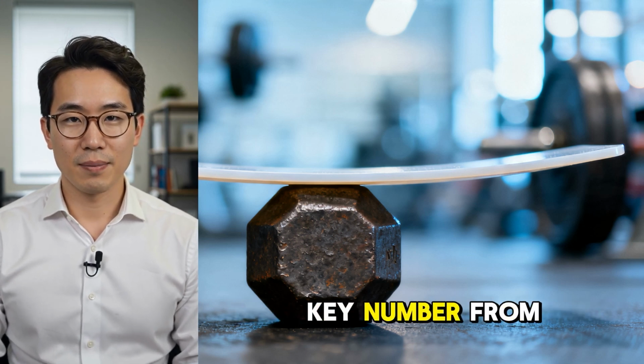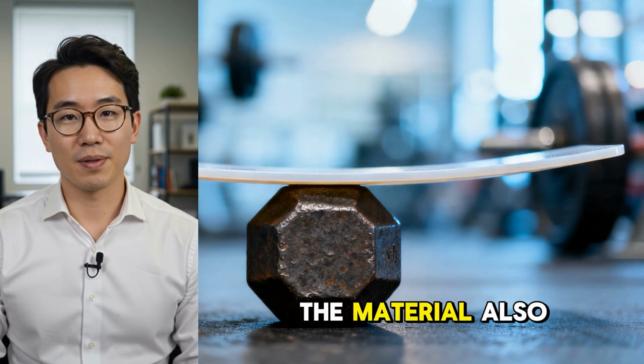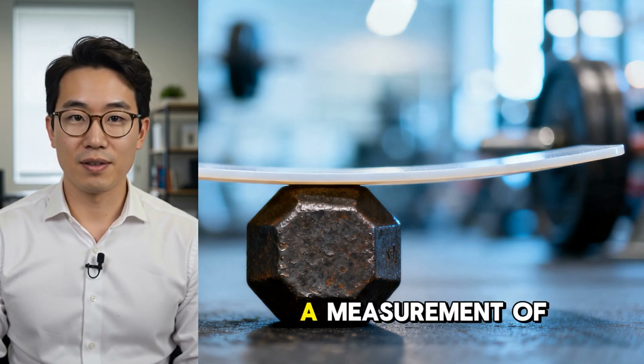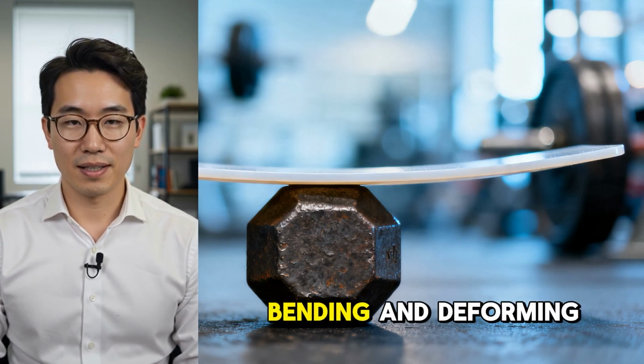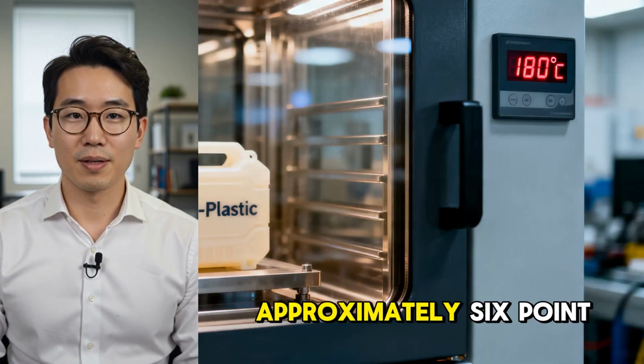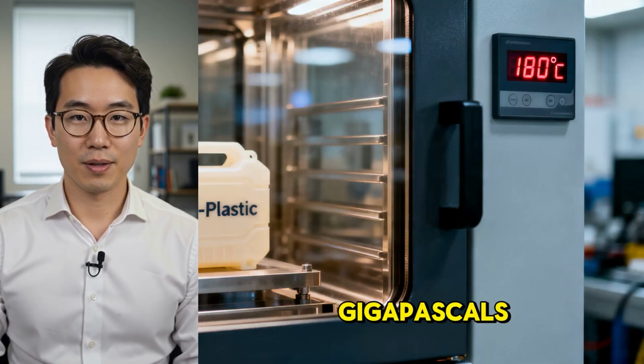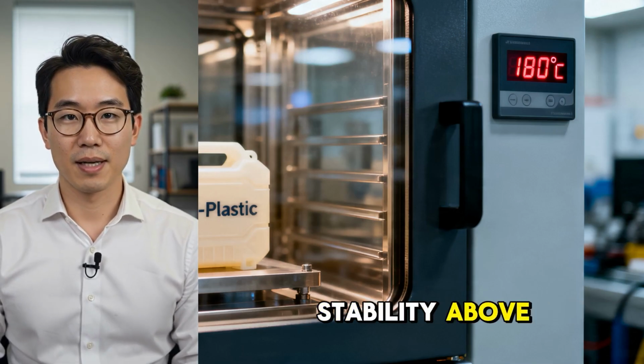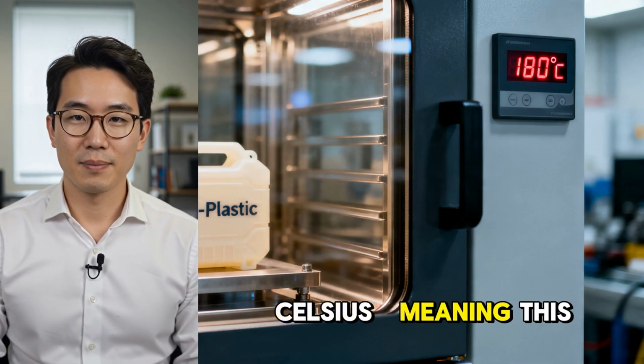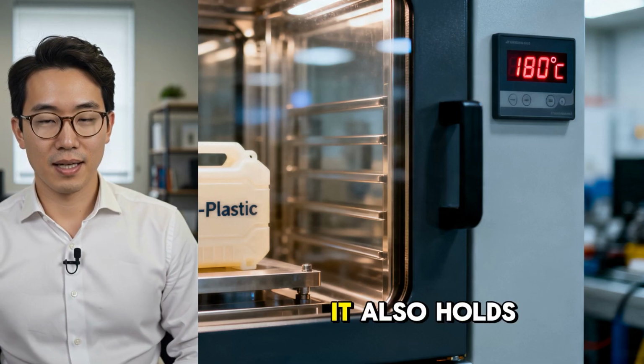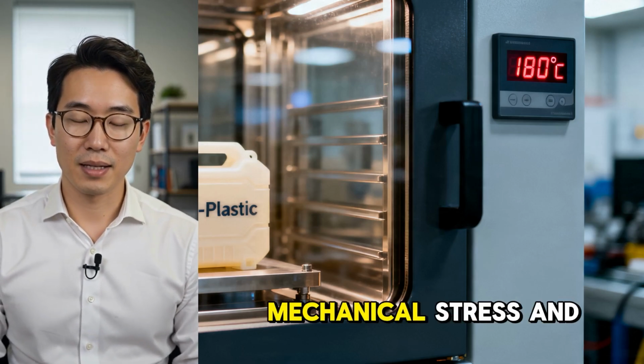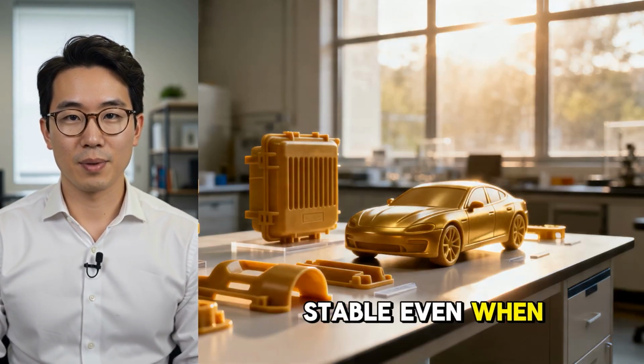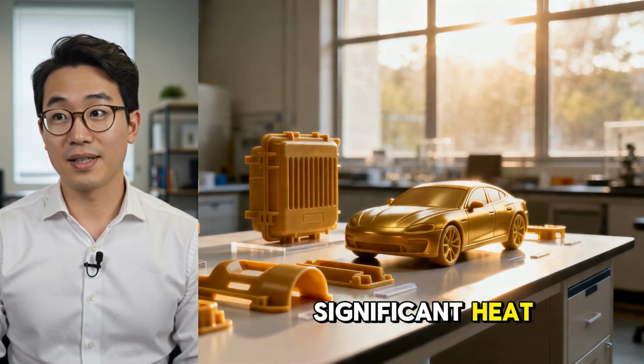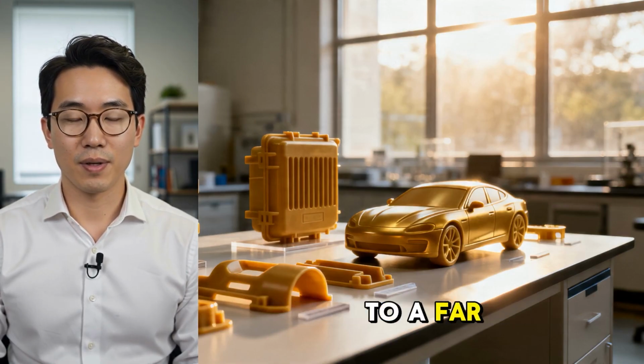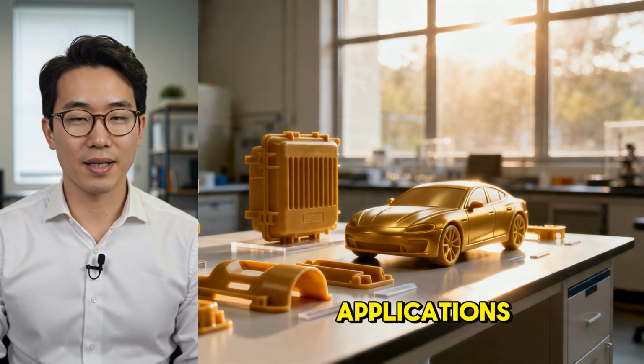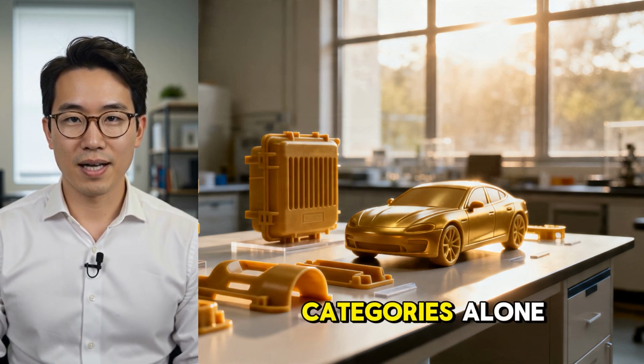Here's the second key number from the same published study. The material also achieved a flexural modulus, a measurement of how well a material resists bending and deforming under load, of approximately 6.41 gigapascals, alongside thermomechanical stability above 180 degrees Celsius, meaning this material doesn't just resist tearing, it also holds its shape reliably under real mechanical stress, and stays structurally stable even when exposed to genuinely significant heat, a combination that opens the door to a far wider range of practical applications than a plastic that only performs well in one of those categories alone.